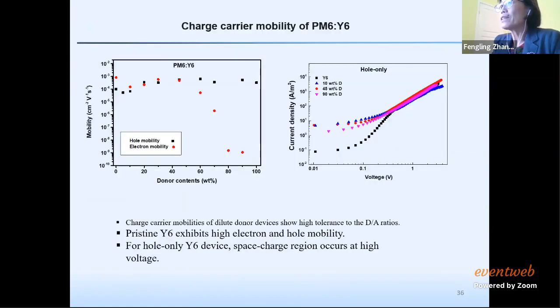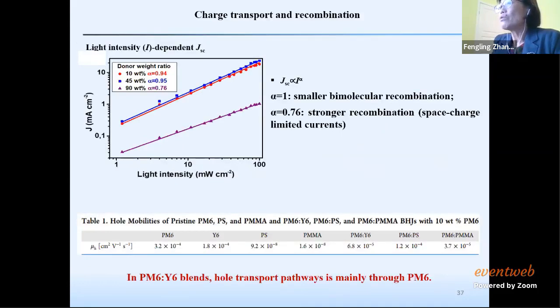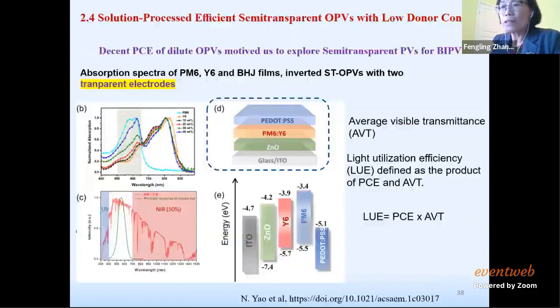So here shows the mobility. From this, we can see the acceptor is an ambipolar material because it transports both holes and electrons equally. So then we want to know if the charge transport depends only on the acceptor. We compare with different kinds of insulating materials. Then we figure out that even with 10% donor, the donor still takes the main role in transporting holes, not so much the acceptor. So it clarifies that the acceptor in the device mostly contributes to the charge generation and the photovoltaics, not to transporting holes.